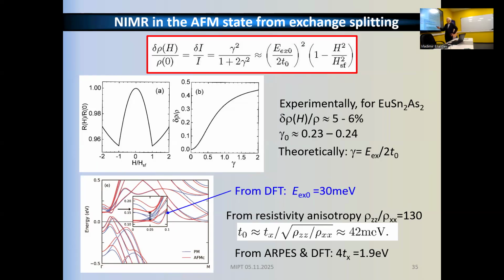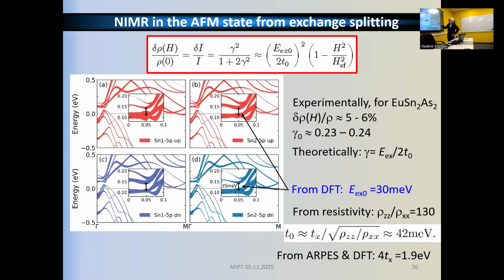And DFT calculations were done by Nikita Pudalov and Vladimir for our material. There is an exchange splitting of an order of 30 meV, but you understand that the exchange splitting is a very complicated phenomenon because there are a number of bands and you have to average somehow. This is just a qualitative characteristic. For example, this illustrates what I said for two different layers. There are two layers in between europium layers. There are two different tin arsenide layers, and for one tin and for the other tin, there is a little bit different band structure.